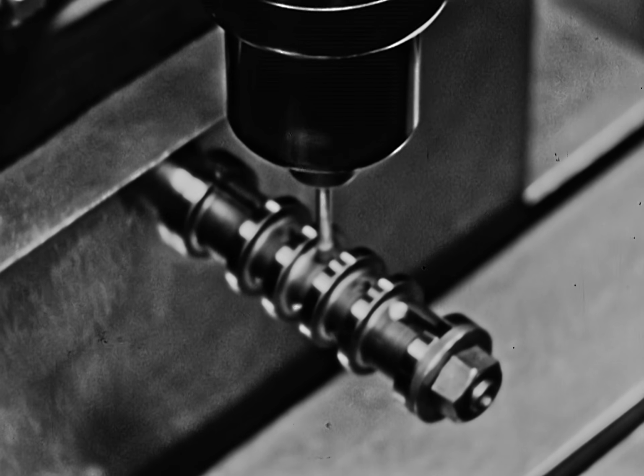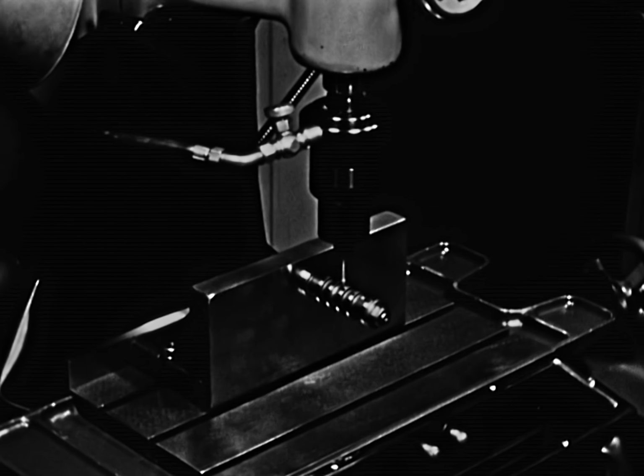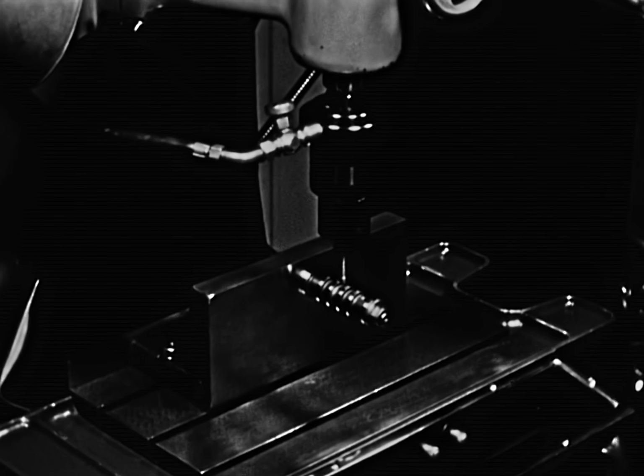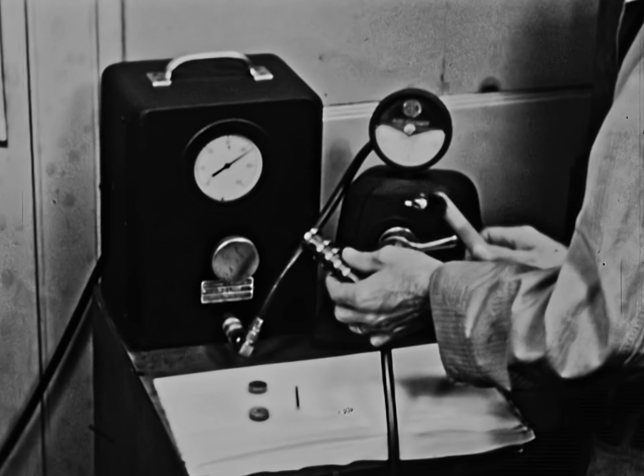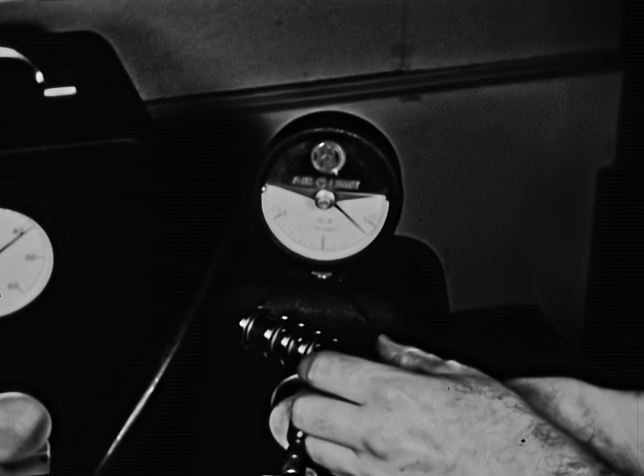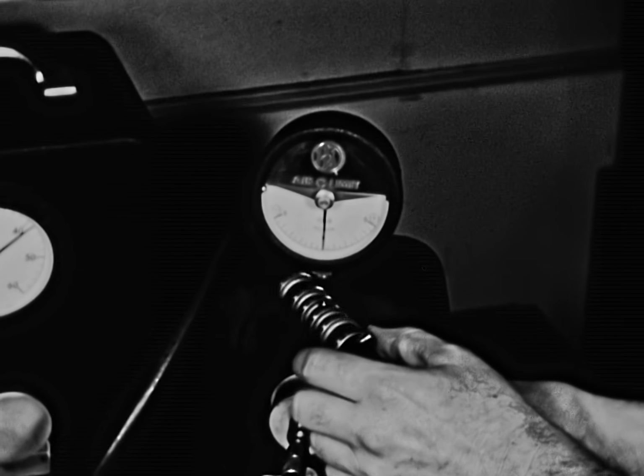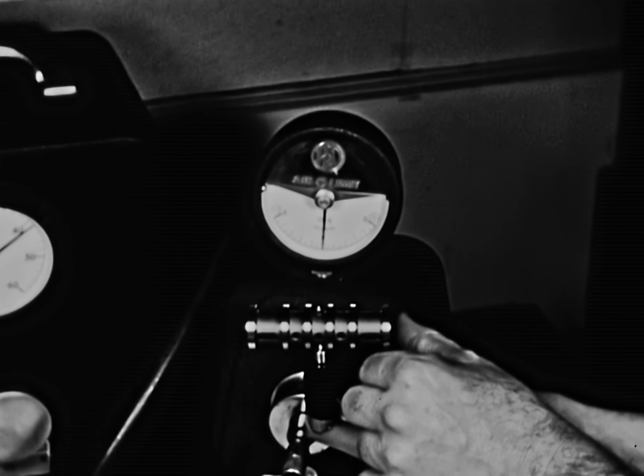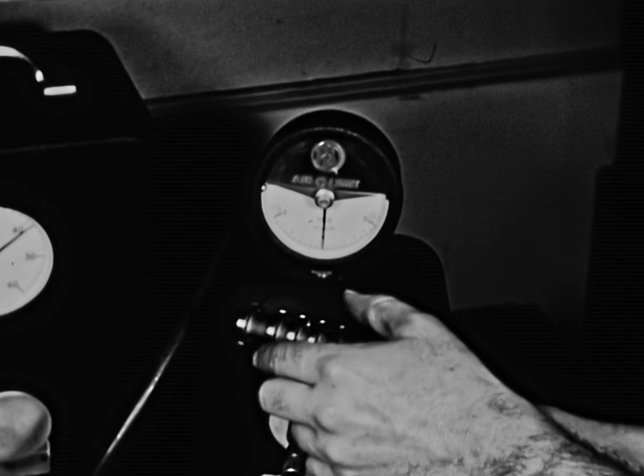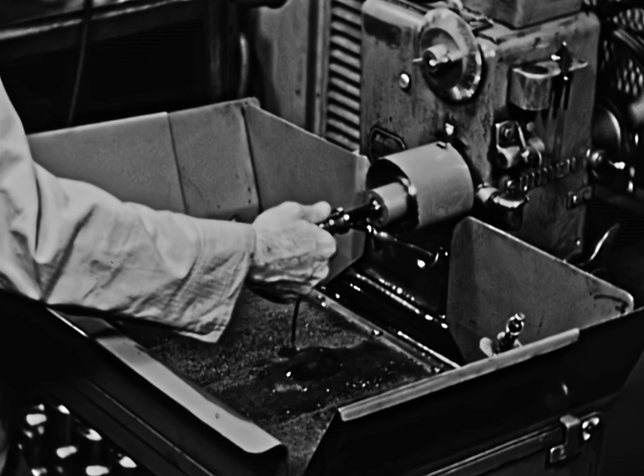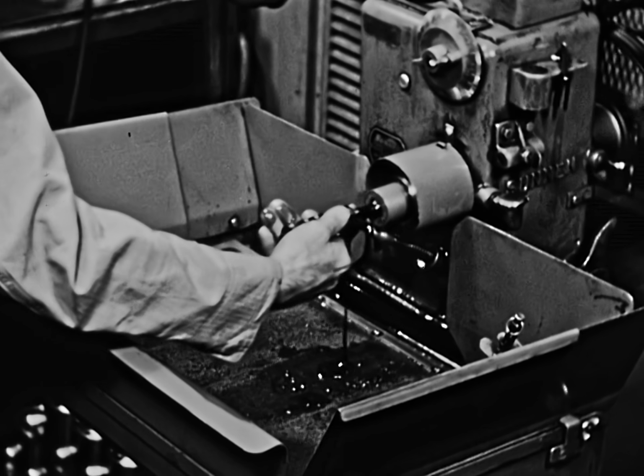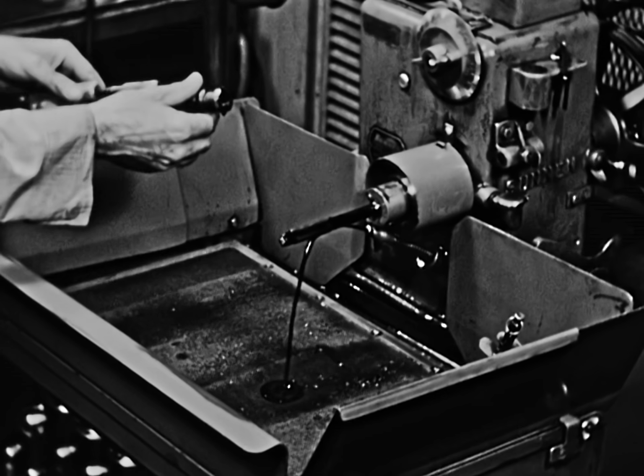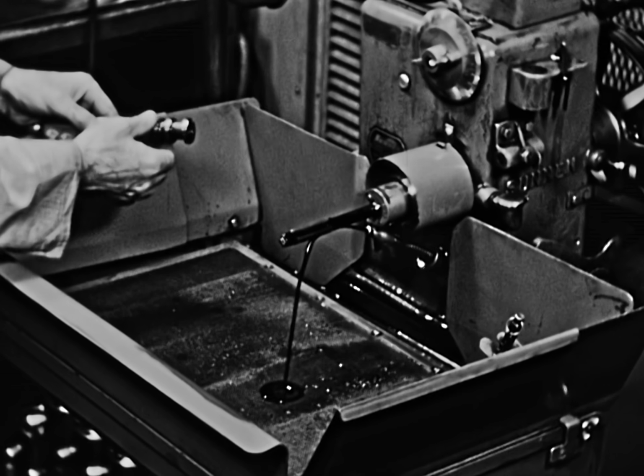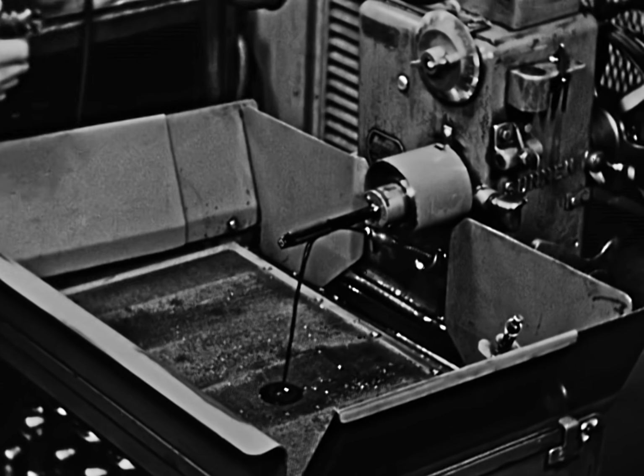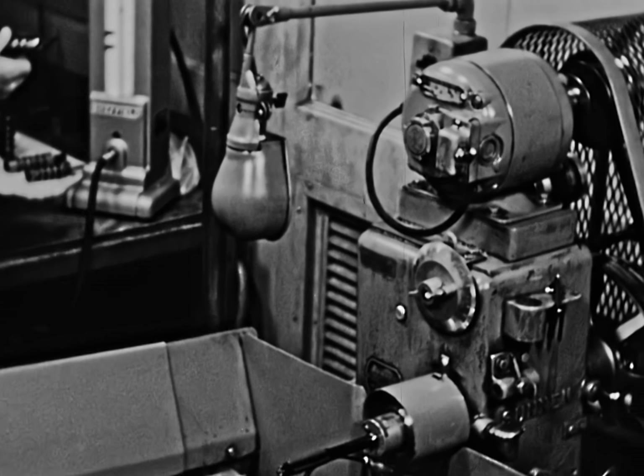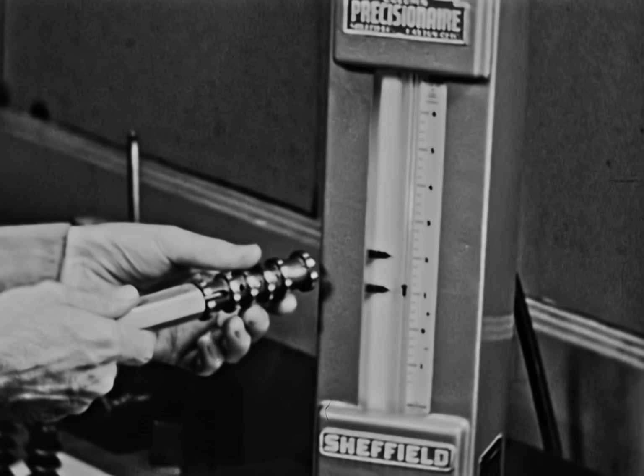3/16" portholes are ground in the valve sleeves with a plus or minus tolerance of only 1/2. The finished work shows only 25 millionths out of round, barely measurable. This is a routine tolerance on this grinding operation. To be equally accurate, the valve sleeve inner diameter is honed to the same exact standards. The high efficiency record of the air gauge tracer is due mainly to the exacting standards that are maintained in construction. This ID shows only a 40 millionths variation.